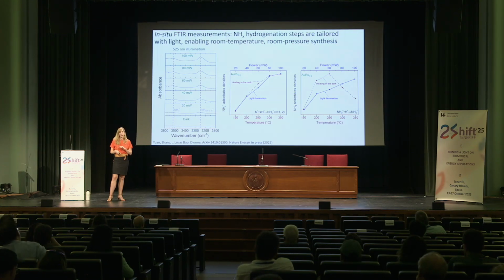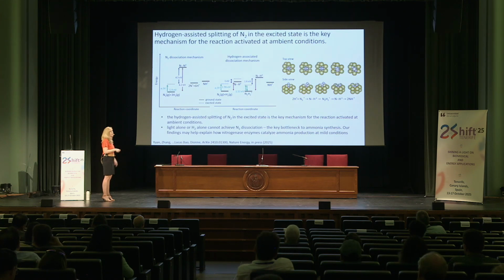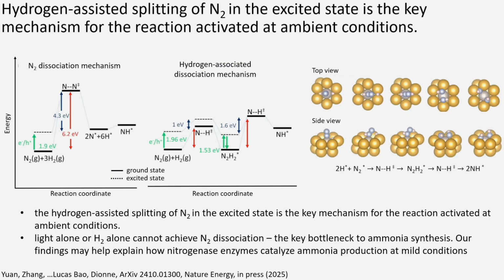So what we're able to do with light is basically change the reaction pathway. And that's illustrated here by some density functional calculations where we do both the ground state calculation shown in bold and the excited state calculation shown in the dashed line, and look at different pathways and how those are modified. So here we're looking at the N2 dissociation mechanism and then the hydrogen-assisted dissociation mechanism of that N triple bond N. And to break that N triple bond N, which is often thought to be the rate-limiting step in ammonia synthesis, you can see whether we're in the ground state or the excited state.